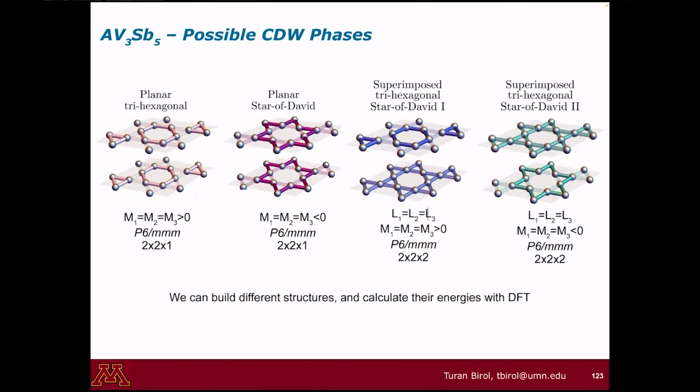The main issue is many of these phases that I mentioned. For example, the two on the right have exactly the same supercell with identical symmetry, literally, so the positions of the Bragg peaks are identical. What you really need is to look at the intensities of the Bragg peaks. Yes. And the displacements we are talking about are not huge displacements.